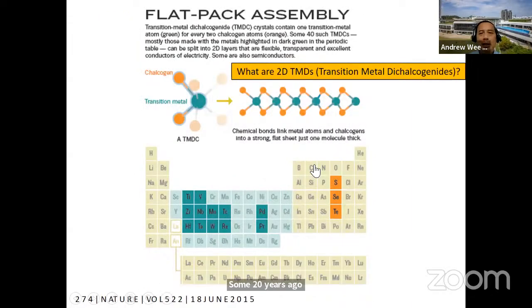The field of 2D TMD stands for transition metal dichalcogenides, in case some of you are wondering. The field of 2D TMDs came about soon after graphene was isolated. And there are many different TMDs that you could get, because you could have a transition metal anywhere from this transition metal series and a chalcogen, sulfur, selenium, or tellurium bonded to it. It has the structure of three atom layers with, right in the center, the transition metal, and at the surfaces, the chalcogen in a ratio of 2:1, as the formula suggests.